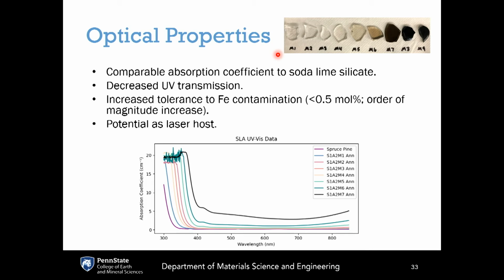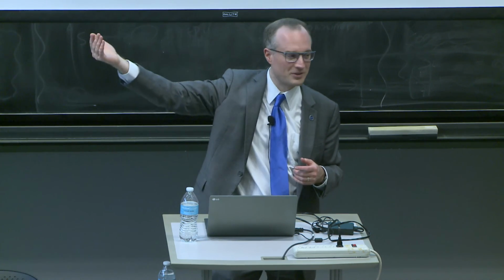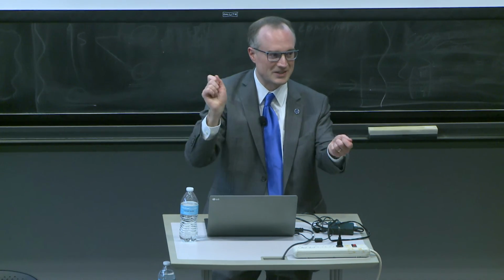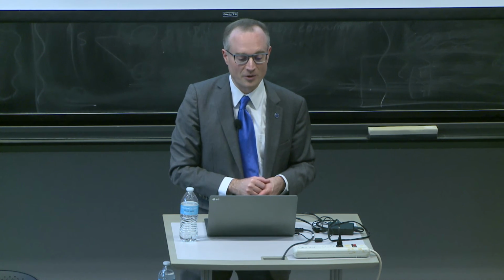Now, if you take a window glass and you turn it on its side to look through the width, what color is it? It's green, right? It's green because it's got trace amounts of iron impurities. You don't really notice it when you're looking through the 3 millimeter thickness, but if you turn it on its side, you can't even see through it because it's so green. With this new glass, it can actually take more iron contamination for the same amount of coloration, which is quite interesting. But if you want to put colors, you can also introduce all kinds of beautiful colors into Lion glass with different transition metal and rare earth dopants.